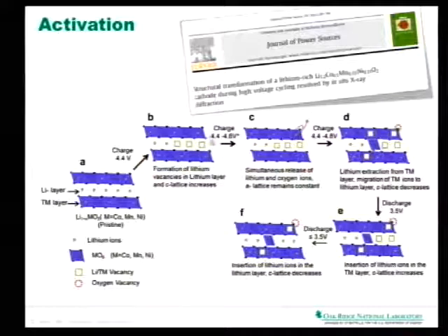Now, the tricky thing is, as you're charging above a certain voltage, all of a sudden other things happen. Not just your lithium ions are getting out of there. You're also releasing oxygen from your oxide layer, from your transition metal oxide layer, essentially. So once that oxygen is gone, you're creating the opportunity for transition metals to migrate around as well. You're creating vacancies there too. And now all of a sudden, everything gets pretty messy. When you put your lithium back, you might not find the same vacancies you had before. Your lithium might migrate between the layers, and it gets really, really tricky. Now, all of this is realized. You see how it is essentially the same crystal structure here in these pictographs. So that gives us a problem.